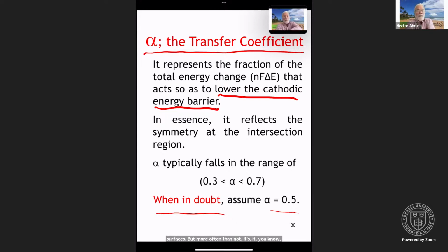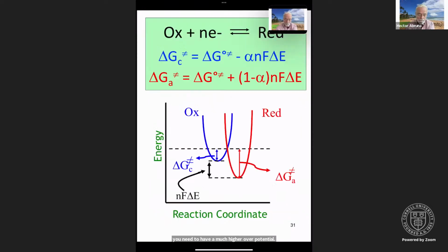If you see anybody claiming an alpha value of 0.1, you should get a little bit suspicious because that's very low. Meaning, in order to effect the same change in the rate, you need to have a much higher overpotential because only 10% of that is going in the direction that you want it to go. And so if we go back then to our previous image, so now we have that the reduction process, the cathodic reaction, has a smaller activation energy to get you to the intersection region. Conversely, the anodic process has a higher energy of activation, the difference being provided by this nF delta E.